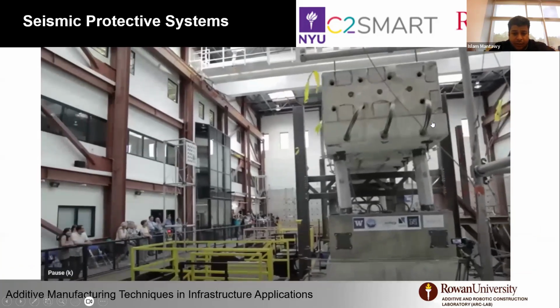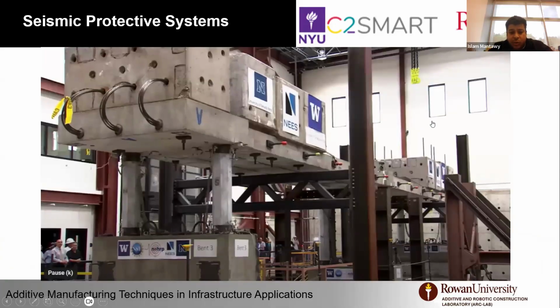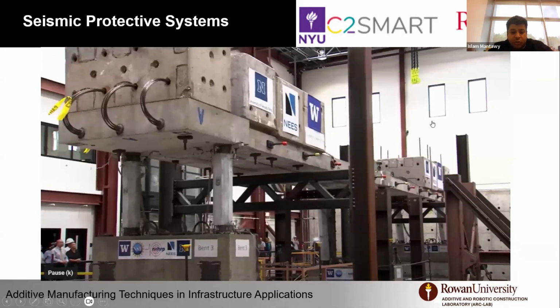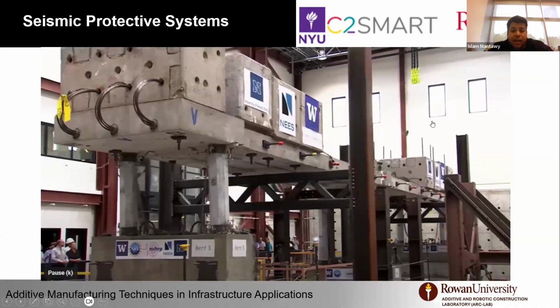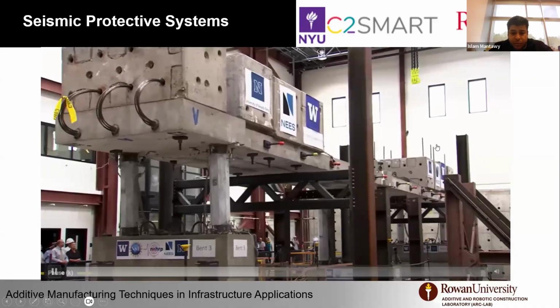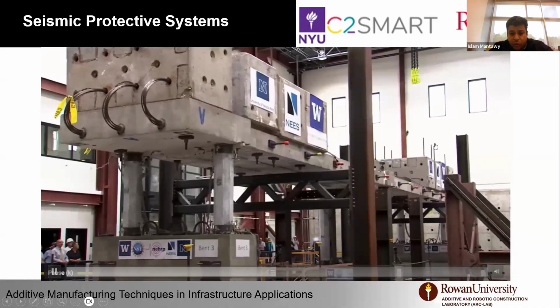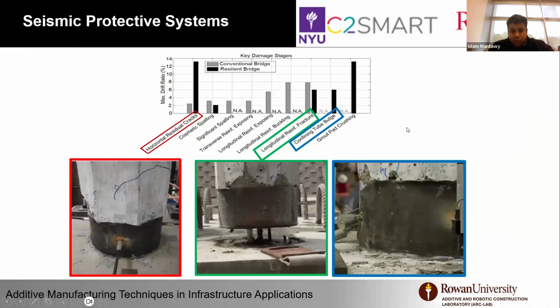As you can see here, significant deformation during the earthquake, but since we are using a pre-tension or pre-stressed strand within the column, it allows us to self-center the column after the earthquake, even during the earthquake also. So what we noticed from a damage perspective is almost no cracks to the concrete, which looks amazing, and the inspector goes and sees no damage. But the main problem was the damage within the column in the rebar, which dissipated energy through yielding and fracture, and also some bulging that happened to the tube.